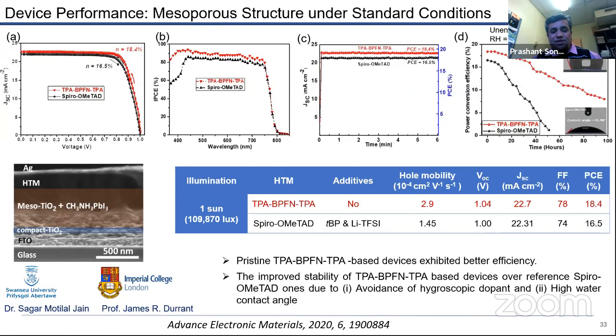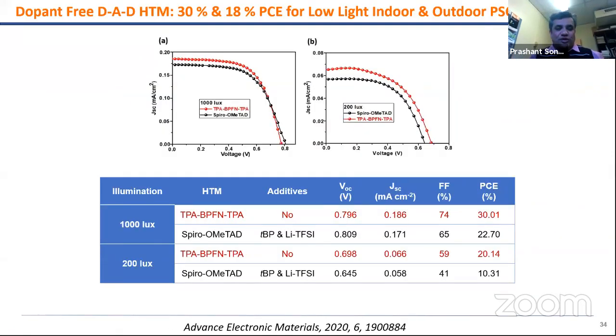Sagar tried to do the low light condition, because not necessarily when people think about solar cells, they should be on a rooftop. They can also have an indoor application. And for an indoor type of application, if you have an illumination of, let us say, 1000 lux with a low light intensity, we can achieve very high efficiency, 30% and 22% for this standard Spiro device, compared with our newly fabricated HTM devices, 30%.